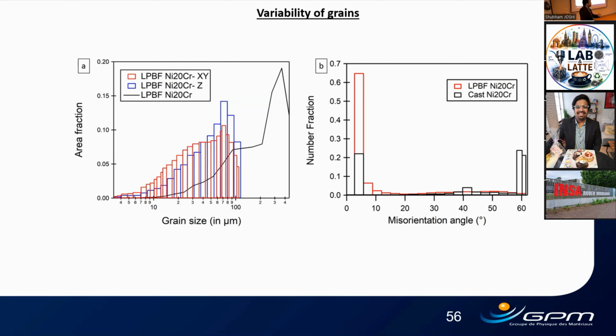Actually, I like that paper quite a lot. In the same paper, what is shown is that when you print in a horizontal direction versus a vertical direction, the aspect ratio of grains remains between 2 and 3 for optimized samples, like if the volumetric energy density is not too high. So we do not have a huge difference in the grain size aspect ratio. So the model might not have huge issues when we consider it for differently printed samples.